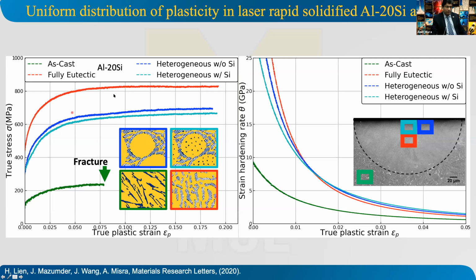I will only show the compression. We are doing tension and we'll do other tests, but it's very interesting that if you compare with the regular aluminum silicon, the textbook eutectic structure, it has very low strength, about 200 or so MPa. And even in compression, you don't get much plasticity in it because silicon flakes that are tens of microns are brittle and there is no plastic compatibility. So you get brittle fracture, limited deformation, even in compression.